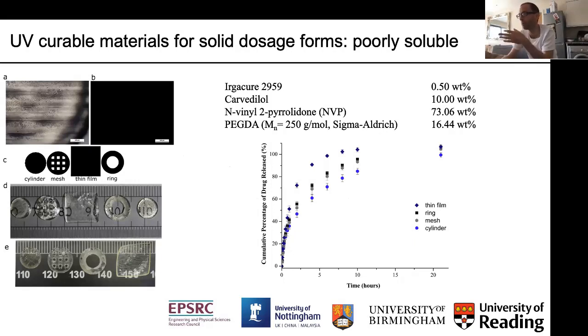We modified the proportion of the solvent in there compared to the water-soluble, and then we were able to print that. We were able to get the drug in, we were able to get into a nice formulation, we were able to print that. And on the left, you can see examples of where we were able to print in various different formulations. So the NVP is a really nice choice because when we cross-link it with the PEGDA, it creates PVP, which is a common pharmaceutical excipient.